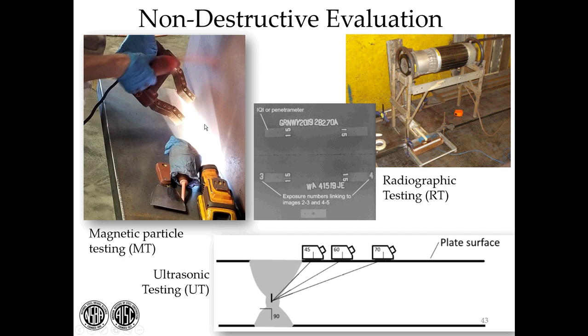They spray down onto the weld, and if there's a discontinuity, such as a crack in the weld, that crack will break the magnetic field that's going through the surface of the steel, as brought in by the magnets. So the powder will accumulate at that crack or discontinuity, and it'll highlight it for you. So it's a good way to go looking for cracks on the surface. In this particular case, you see it being used on a final condition. Fabricators may also use it in process on welding if they're in a constraint situation and want to make sure that they've gotten everything out in the groove of a weld and make sure that it's clean. They might use magnetic particle as well.